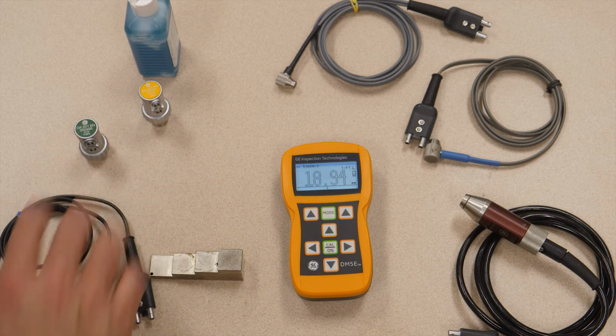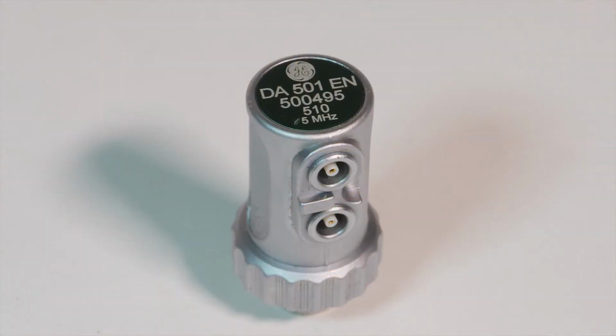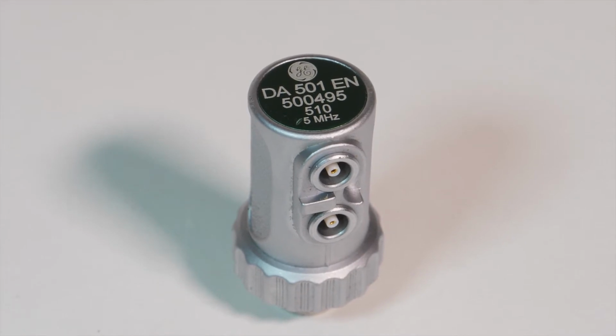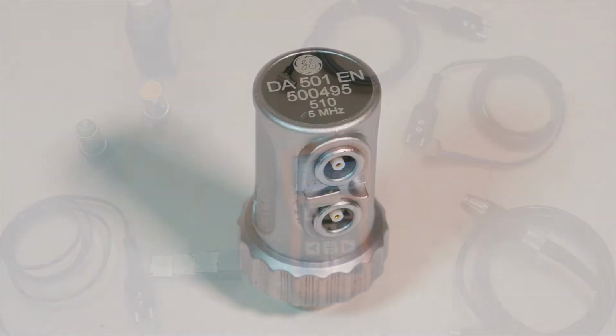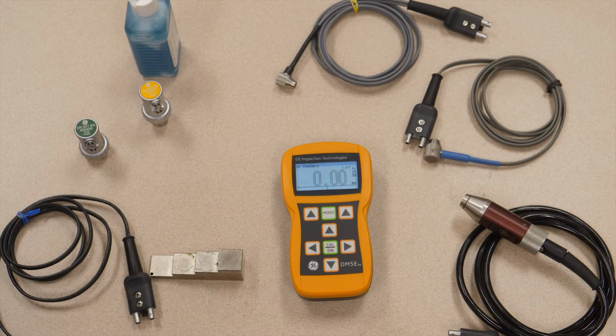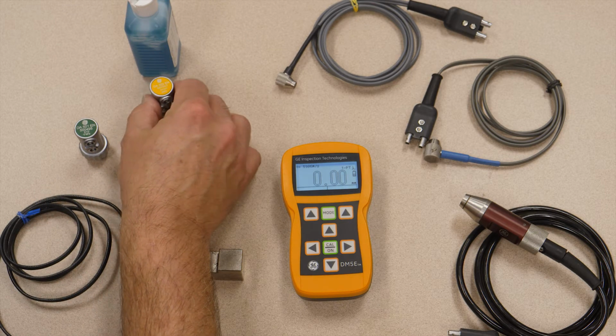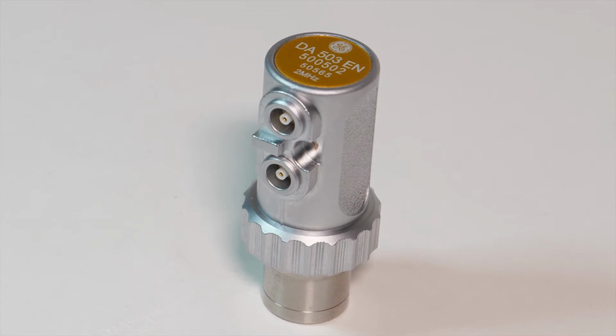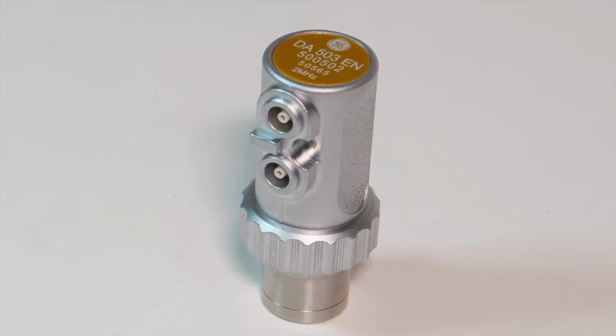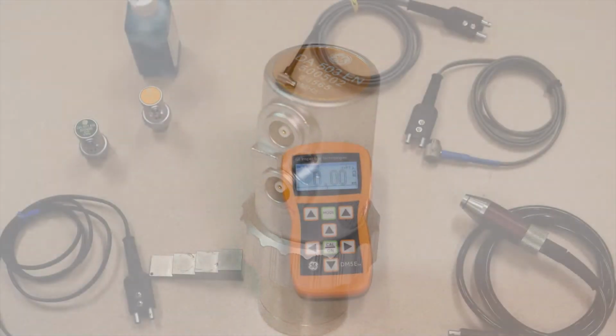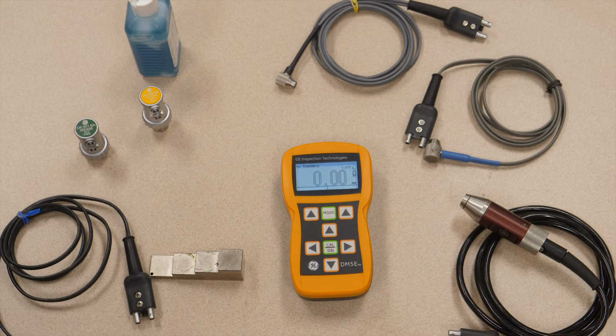The DA501 is probably the most commonly used probe with the DM5E. It is a 5 megahertz general purpose probe, has a measurement range of about 1 millimeter to 200 millimeters, 0.04 of an inch to 8 inches. The DA503 is a lower frequency, larger diameter probe. It is ideally suited to coarse grained materials, highly attenuative materials, thicker materials. With the DA503, you have a measurement range of 5 millimeters to 300 millimeters, or about 0.2 to 12 inches. All right, so thicker materials, DA503.